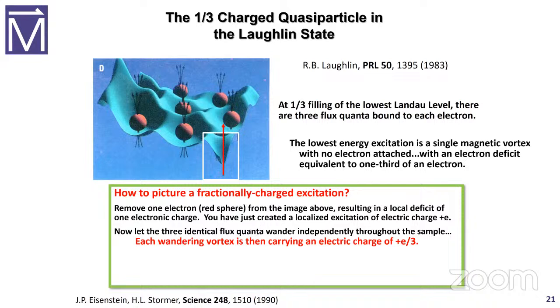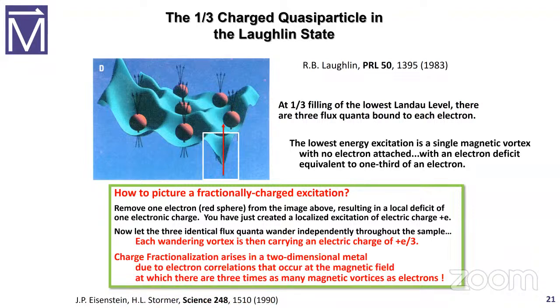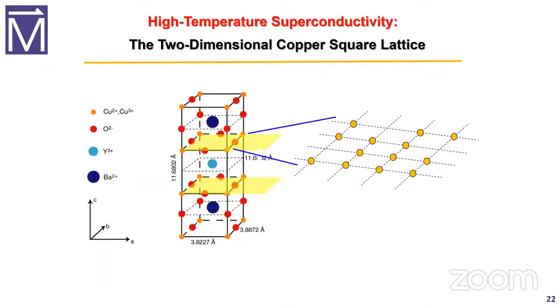So now here I've got one place where the lowest energy excitation is a single magnetic vortex with no electron attached, with an electron deficit equivalent to one third of an electron. So this is the lowest energy excitation. It's one extra vortex in a one-third Laughlin state, and it has precisely e over three electric charge. It sounds like it might be related to quarks. Nobody's found a way to find that link. But charge fractionalization arises in a two-dimensional metal due to electron correlations that occur at the magnetic field in which there are three times as many magnetic vortices as electrons. So high energy physics has quarks, condensed matter physics has fractional charges, and these have been measured to a precision of a few parts in 10 to the eighth for the electric charge. It's insanely precise at one third.